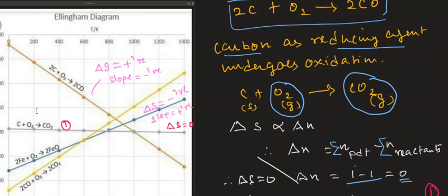So in the case of iron, that combines with oxygen to give iron oxide. So it gives 2 moles of iron oxide. Of course, this is solid, is it not? So when it is solid, now product minus reactant. What happens here? There is no gaseous product. So minus reactant, there is 1 mole. So it means minus. So when delta S is minus, that is negative, the slope is positive. Okay. So you can see almost all metals will be behaving like this only, with a positive slope.